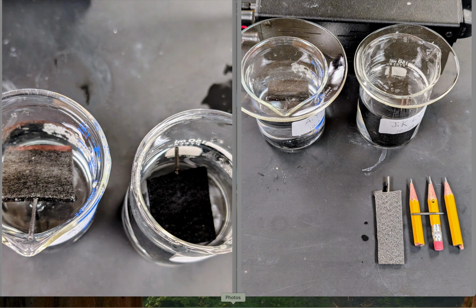And the reason it's darker, when you start, the graphite felt is usually gray. There's a big difference between the two. You can even see it there before and after this run, the difference in coloration. Because when you disrupt the pi network of the graphite, which is, of course, conducting, you're disrupting and spacing fibers with the oxidation, letting more visible light in, hence the black color.